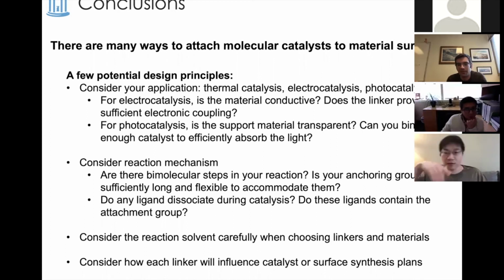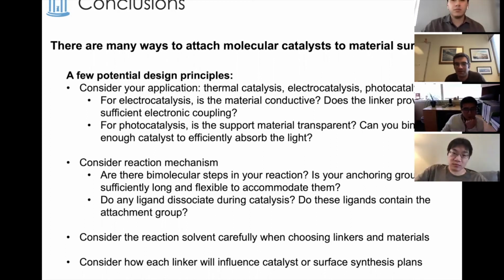So my advice is to always consider your application first. What's the reaction you want to run? What are the conditions of it? Is it a thermal reaction or an electrocatalytic reaction or a photocatalytic reaction? And that has big implications in what your support material should be. If it's an electrocatalytic reaction, you need a conductive support material. You need to worry about how well your linker is going to couple to the electrode surface. Are you going to have slow or fast electron transfer between the electrode surface and the attached catalyst?